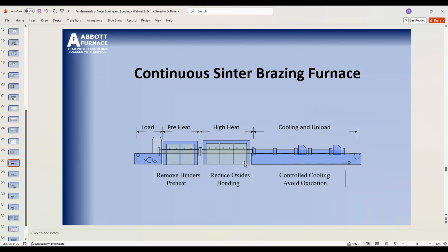So now let's relate this to our sintering process, right? We've talked about brazing. We've talked about the gap. We've talked about having a clean part. We've talked about controlling, getting all the oxides off the part. We talked about putting a real thin layer of that carbon in the pores and in the joint there so that there's still enough capillary pull through the braze joint, but the pores no longer have that real strong ability to pull it, to steal it, right? So we, the gap and the chemistries and all of that, and cleaning the oxides. But now let's relate this to our sintering process as well.